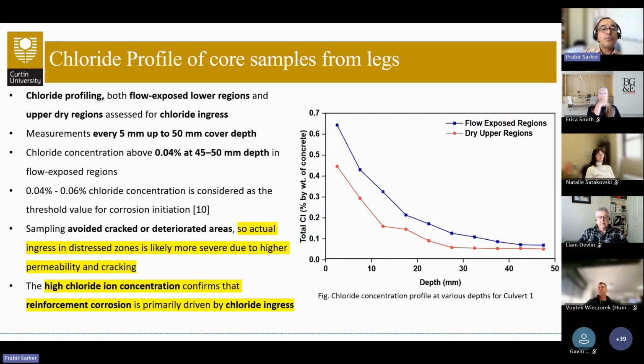The chloride profile of the core samples collected from the site was tested in the lab, and we plotted the chloride profile. The horizontal axis is the depth from the surface towards the reinforcement, and the vertical axis is the total chloride content as a percentage of the mass of concrete samples collected from the core.